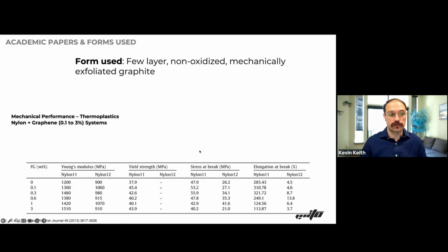Another paper, they introduced graphene into nylon 11 and 12, anywhere between 0.1 and 3% standard compounding. And so what we saw is that the Young's modulus in nylon 11 really worked at a really high 3% loading, but you saw it still improved the values 10-15% at the 0.1 and 1%. It kind of looks like a little bit of a bimodal bell curve, and the fact that it jumped when you went from 0 to 0.1, it dips at 0.3, 0.6, and then it jumps back up at 1%.